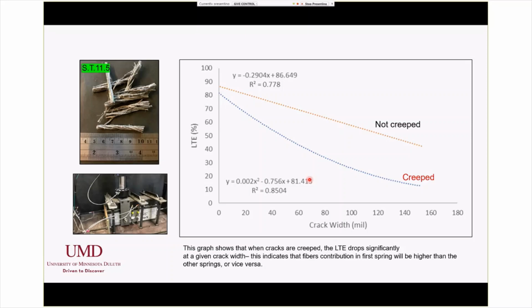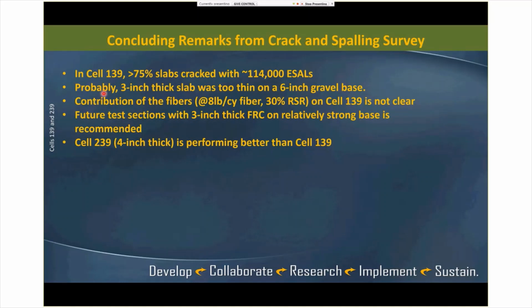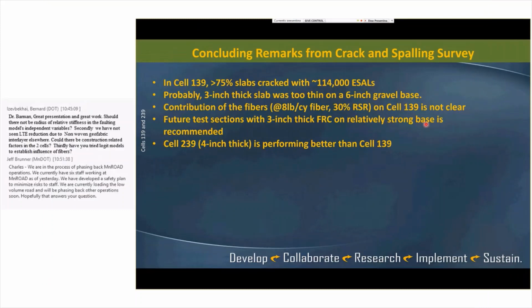So in the conclusion, regarding the crack and spalling, in cell 139, as we saw, 75% of the slab cracked. Probably the 3-inch thick slab was too thin on a 6-inch gravel base. So the structure was actually thin, and we probably cannot comment whether fiber was really doing anything in cell 139. The structure was probably insufficient. So maybe next time we should either construct thicker cells, or construct the 3-inch layer on a relatively strong base. Then we can compare.